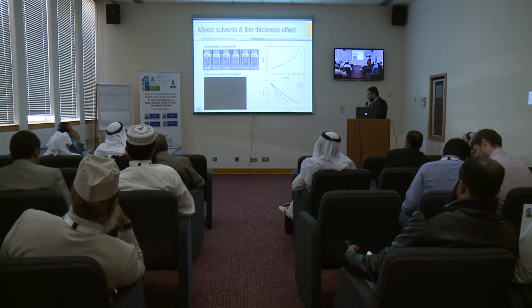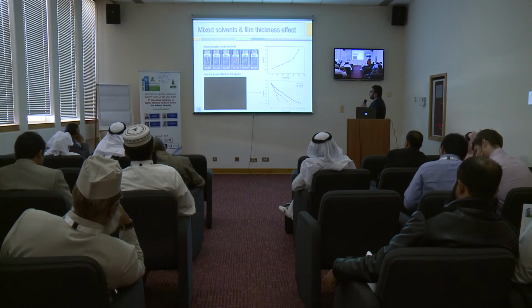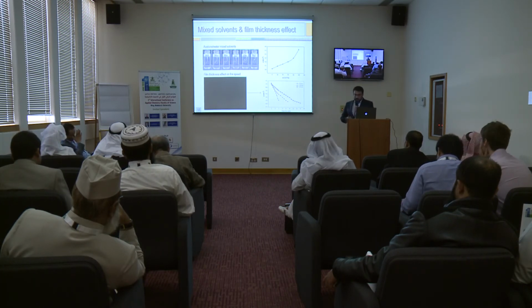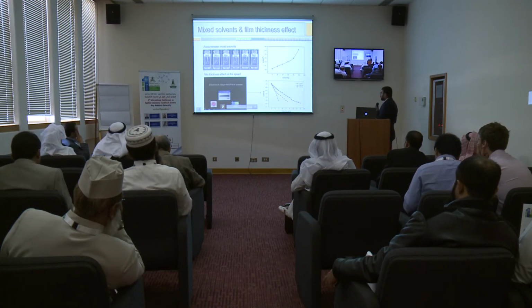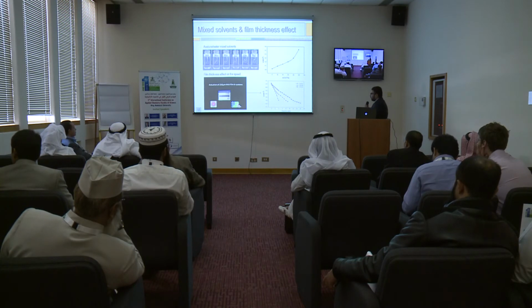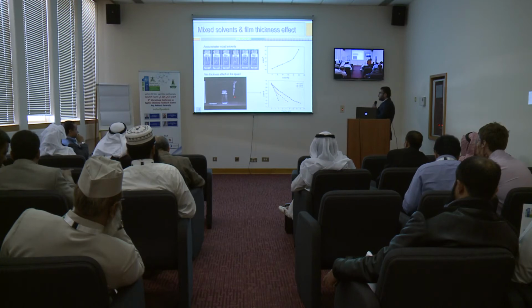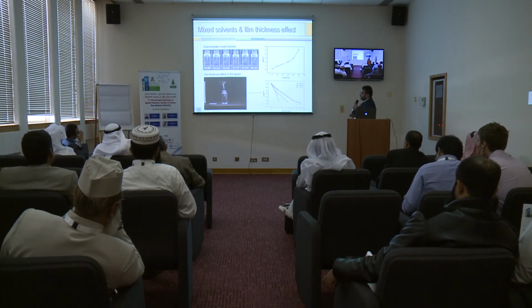Okay, next I used different acetone and water mixed solvents, and I varied the acetone content in water. We can see that the composition dependent curvature was obtained in these experiments. I also made polymer actuator films with different thicknesses, because actuation time is also important for actuators. So here is a 250 micrometer thick film, which showed quite longer time for full opening of this actuation motion.